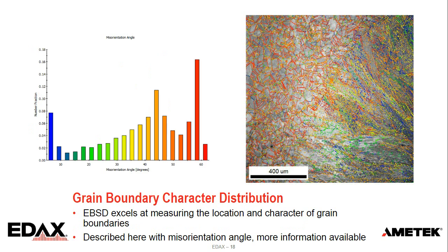One of the things EBSD really excels at measuring are grain boundaries, and what I've called here the location and character of grain boundaries. And what that means is we can tell what the misorientation between 2 pixels is. We measure that angle. We use that when we created the grain tolerance angle. So if it's a misorientation that's between, say, 20 and 25 degrees, we can color it one value. If it's between 40 and 50 degrees, we can color it another value. And so we can measure lots of grain boundaries with EBSD. It's really the most efficient tool for looking at this orientation information because we can look at a large area with fine spatial resolution.